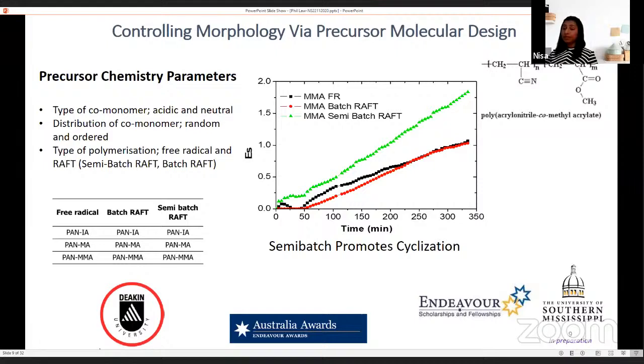Once we completed the synthesis, we conducted stabilization studies on these polymers. This is the most critical and time-consuming step in carbon fiber manufacturing. During this stage, the fibers attain the stability to withstand high temperature carbonization. We found that the polymers synthesized by controlled polymerization promote cyclization reactions, and thereby the stabilization process.